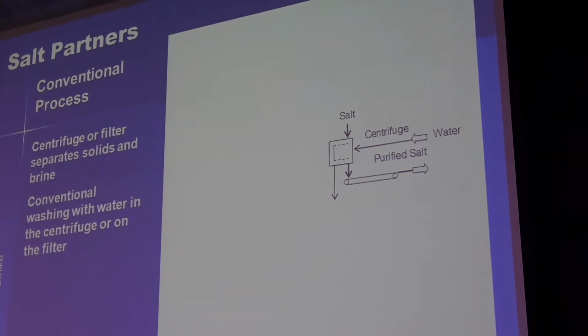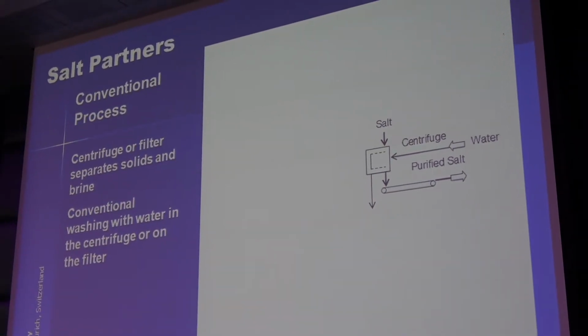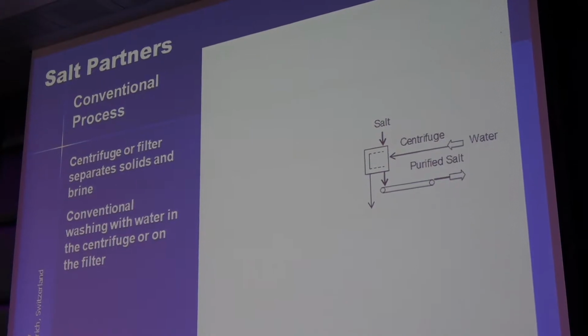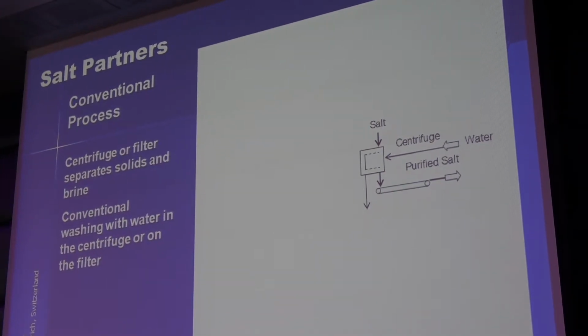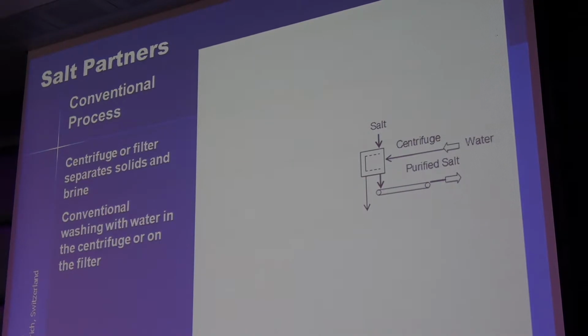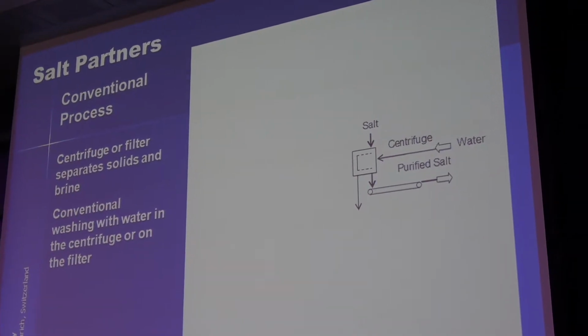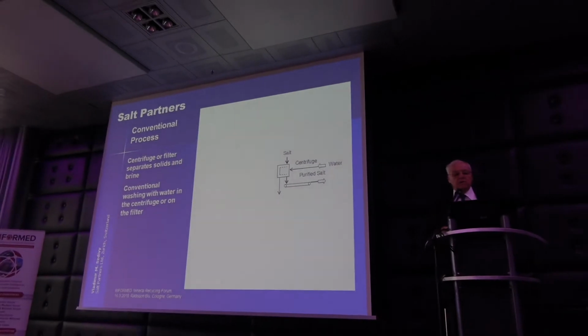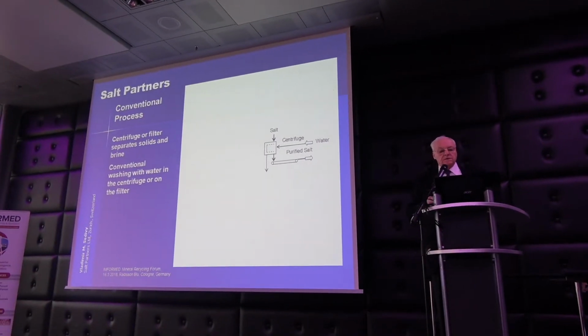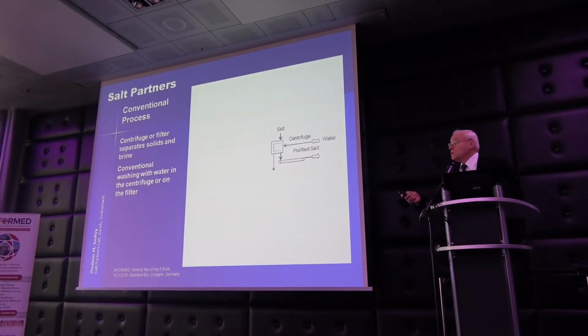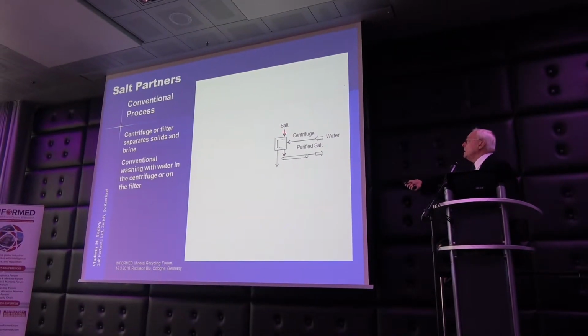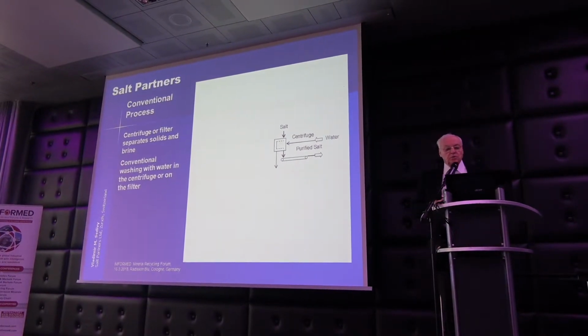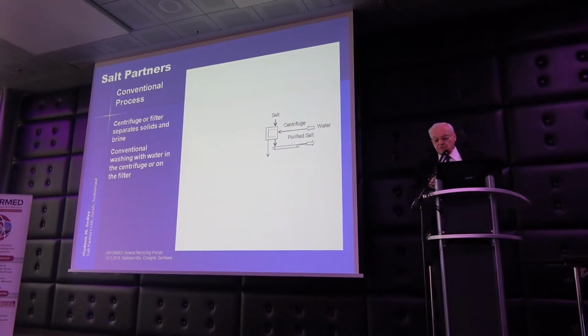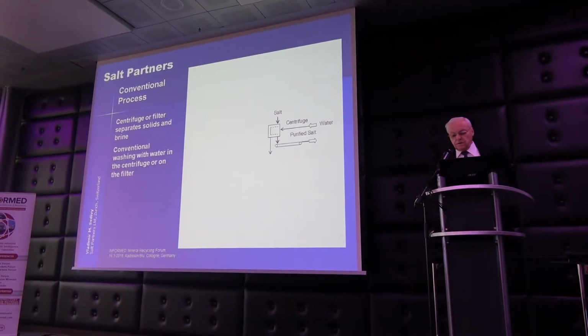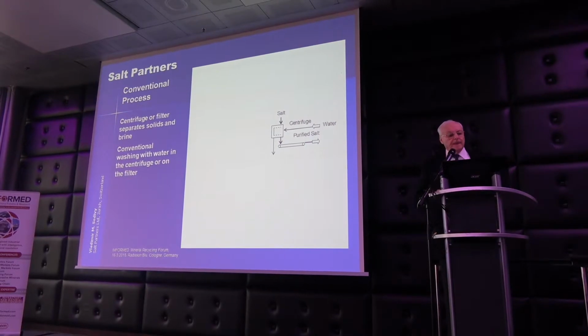process works. The conventional process is that you mix water with some solids, you dissolve what is soluble, and then you separate it, for example, in a centrifuge, but you can also use a filter for that. You get, on the one hand, the feed, shown as the salt here. Then you put the water and you get the purified salt, or in this case the purified salt-free slag.